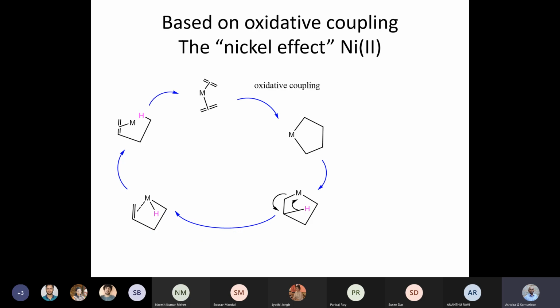And this oxidative coupling was in fact accidentally found out by none other than Ziegler. And if I tell you this, this should not give you the impression that if you are careless in your research, you will make great progress. Because what happened was a PhD student took a reaction vessel, an autoclave, which was not properly washed, and he or she did a polymerization reaction. I don't know the identity of the student. I have not read the original papers, but the story goes that a catalyst that was used in the previous reaction was a contaminant in the Ziegler study of the Aufbau reaction.